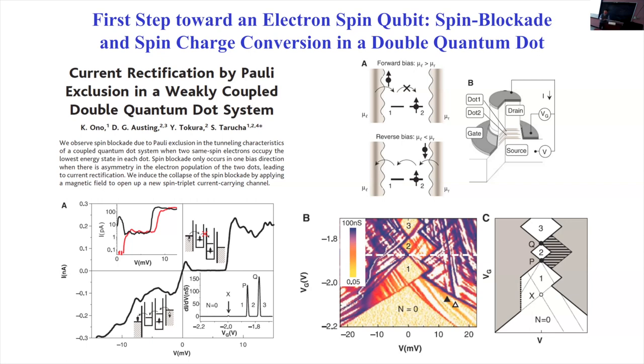Okay, so now you can imagine if you have a charge sensor nearby the double quantum dot that can sense the charge distribution, then by measuring the charge distribution, you can infer back to what the spin configuration was. And even back in the late 1990s, there were already very good charge sensors available that can detect a fraction of a charge. And so this particular experimental discovery allows us to establish correlations between the charge distribution and spin states, and then by measuring the charge, you can infer back to the spin state. So that becomes an important way to measure semiconductor spin.